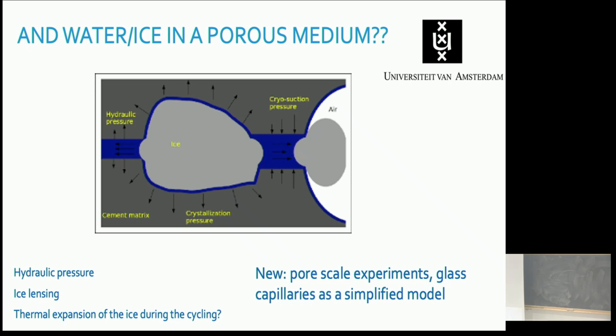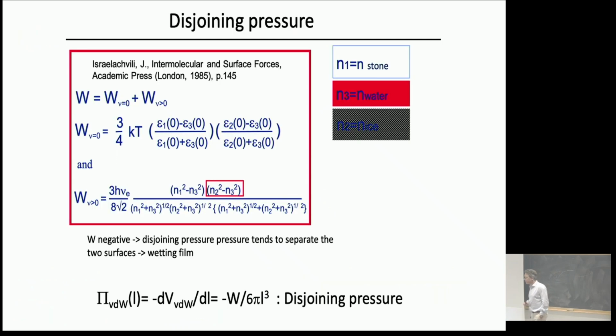So what we did is we made a very simple cartoon experiment of a part of a porous medium. We do a single pore and look at what happens. From what I told you previously, we can already anticipate that there is a liquid film. If I do the calculation of the Hamaker constant, giving the interaction between surfaces 2 and 1 with a layer of medium 3 in between, I can have either sign. I can have an effective disjoining pressure that tends to approach the two surfaces, and then I won't get a film, and I can have an effective disjoining pressure that tends to separate the two surfaces. And then of course the phase number 3, which is water, will come in between.